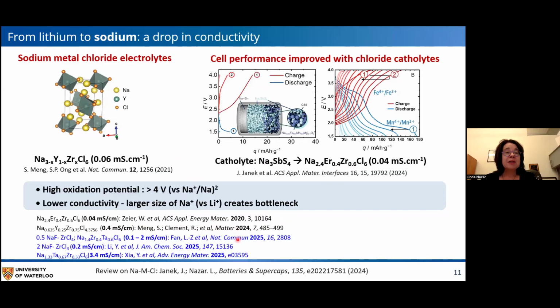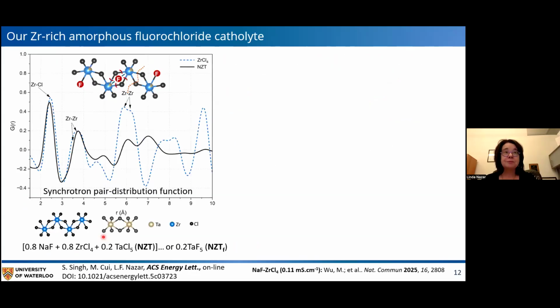And just this last year, because we're in 2026 now, there were 3 very interesting materials reported based on an amorphous structure. And the amorphous nature of these materials seems fairly critical to inducing better, we'll say, conductivities. And in fact, this group, Xia's group, even got up to 3.4 millisiemens. So that's kind of exciting. And we started our work last year as well, trying to use a similar approach to developing new materials, not necessarily crystalline, but quasi-crystalline or nanocrystalline, or as I said, fully amorphous.